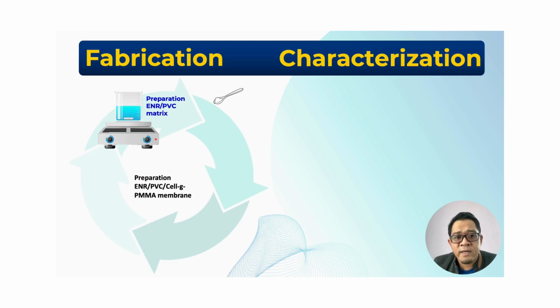6 grams of ENR is soaked overnight in 80 ml of THF and agitated until homogeneous, then mixed with 4 grams of powdered polyvinyl chloride. The ratio of ENR to PVC is 60:40, whereas the ratio of the matrix to THF solvent is 1:8. The phase inversion solution molding is used to generate the ENR PVC cellulose PMMA thin film.